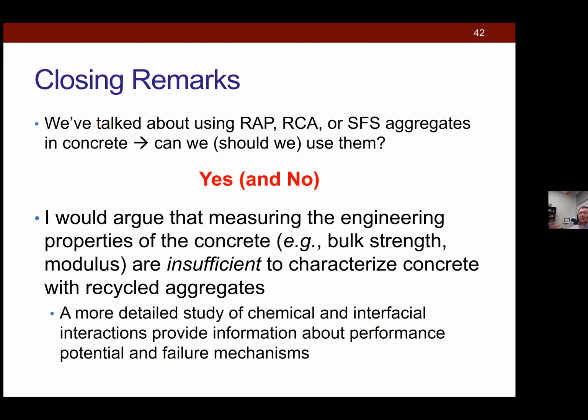Yeah, especially since we've done those studies with RCA, and we were able to track pretty much slump loss in conventional concrete. And since oven dry RCA wants to absorb a lot of that moisture, your slump loss just plummets. You run out of workability fast. And with something like partially saturated, it's workable for a few hours. So I would not be surprised if you see something similar even at these early ages with RCA. It would be interesting to extend your study, just do a few experiments to see what happens if you use RCA in an oven dry condition versus something partially saturated.